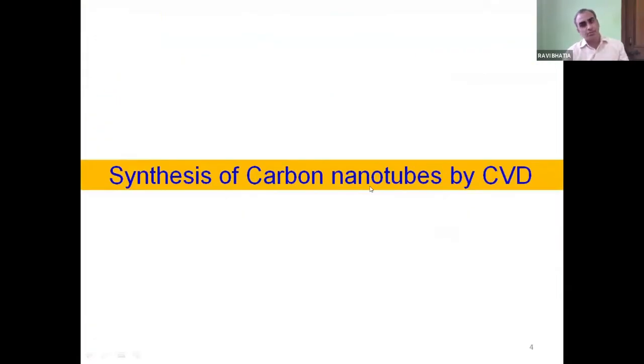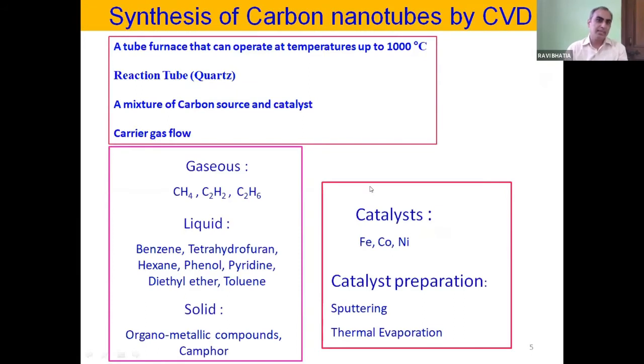Synthesis of carbon nanotube by CVD. Generally, a tube furnace is required which can operate up to 1000 degrees C. As I mentioned, the other two, arc discharge and laser ablation methods, involve very high temperature of the order of 3000 degrees C. Here 1000 degrees C is enough to produce carbon nanotube. Actually, the range of temperature required to produce CNT with CVD is below 1000 degrees C. Actually, at 400 to 900 degrees, it can be grown.